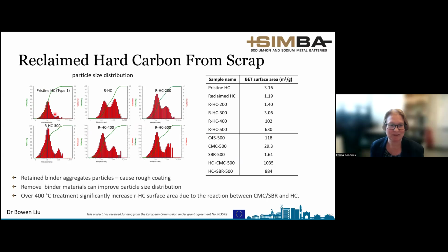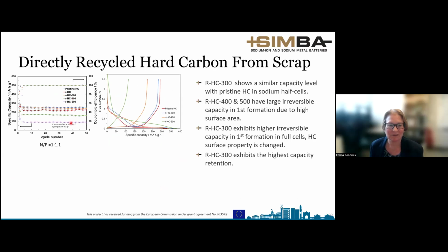And you can see that the pristine particle size is about 10 microns. And when the binder is still present, you have a much larger agglomeration of about 100 microns in this case, even after grinding. But we do get a much better particle size when we decompose the CMC and the SBR at about 300 degrees C. It doesn't decompose the SBR fully, but it does kind of denature the CMC somewhat. And looking at this, we can start to think about reusing it.